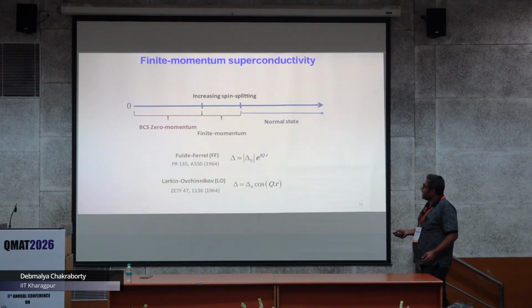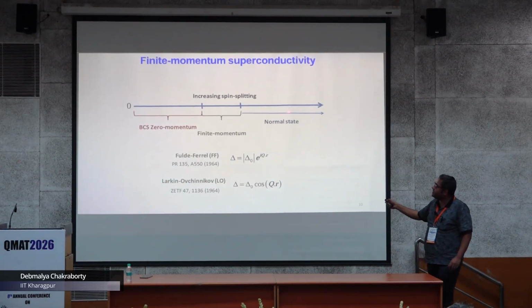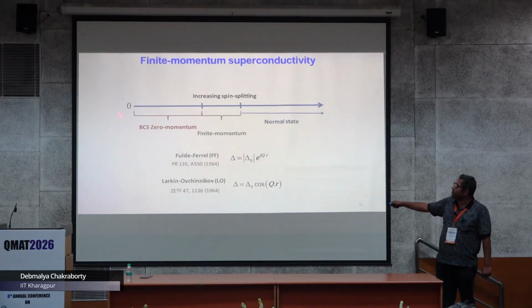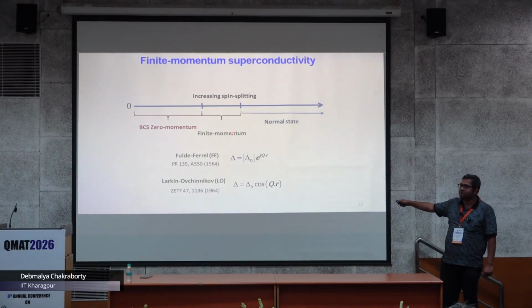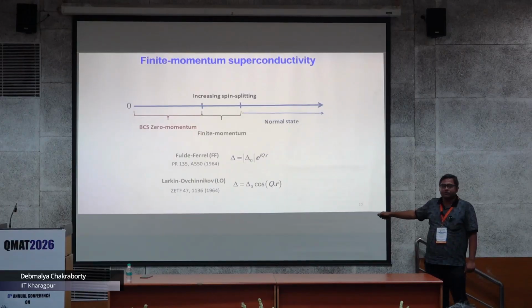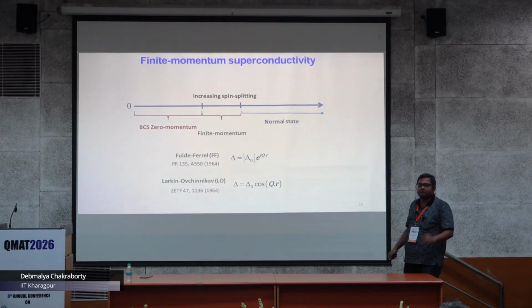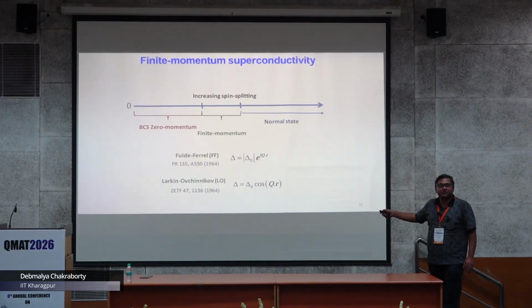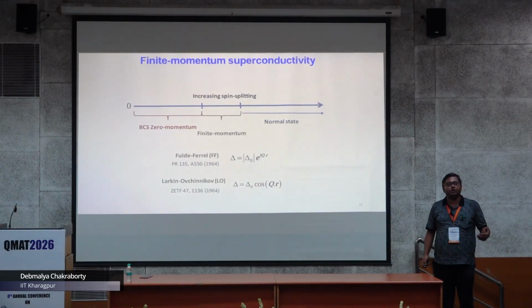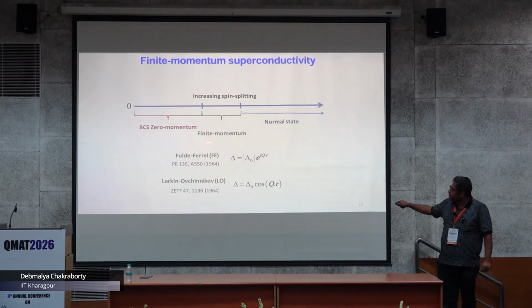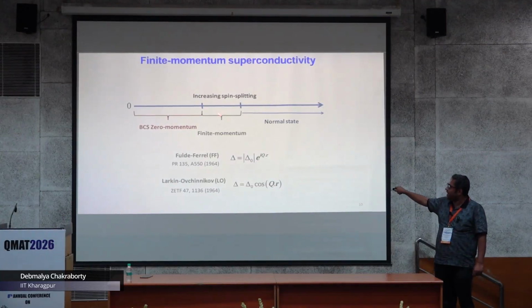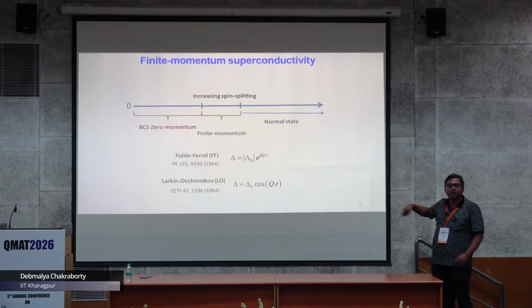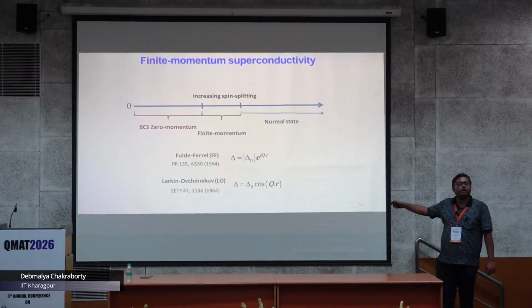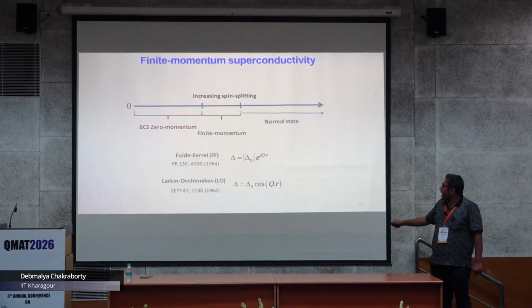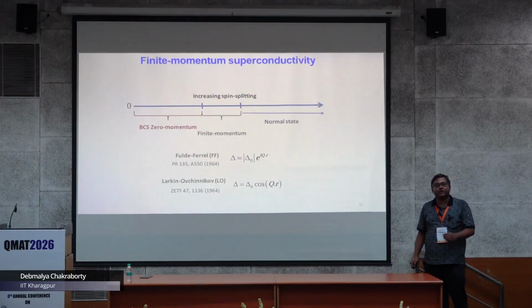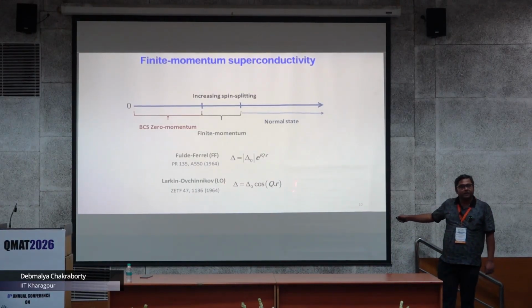This was long known: if you increase the spin splitting, then you go from a zero momentum BCS state to a finite momentum state, and to a normal state eventually. This, again, as Professor Singh mentioned in the last talk, is from 1964, Fulde-Ferrell and Larkin-Ovchinnikov. I just want to add one thing: Fulde-Ferrell said that the order parameter will have a finite q, with an exponential, a complex phase e to the i q dot r, a changing complex phase. However, LO, which is Larkin-Ovchinnikov, has a real order parameter which modulates.